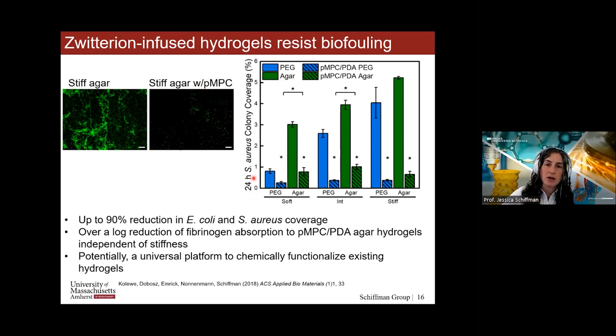And here I have how many MRSA, how many Staph aureus attach to the gel after 24 hours, as a function of our gels. Agar is green, PEG is blue. And just for the sake of example, if we look at our stiff agar as we made it without any polymers, our as-made agar is covered with that bacteria. But if we add in just a little bit of dopamine and the polymer pMPC that gets glued there, our agar is as fouling resistant as our starting anti-fouling PEG gel.